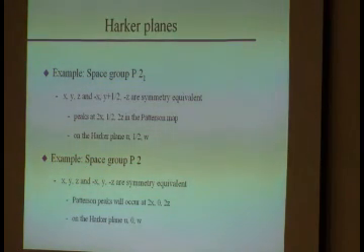Now, let's look at what happens when we have a one-dimensional symmetry element. Some kind of axis, rotation or screw axis. We get Harker planes. Okay? Why? Because now we have symmetry equivalent positions, x, y, z, and x bar, y plus 1/2, z bar. Okay? What's the difference between these? 2x, 1/2, 2z. So that means there are two variables in here, and you will get peaks along the Harker plane u1/2w. Same way you could do this with P2. Okay? In this case, you will get u0w.